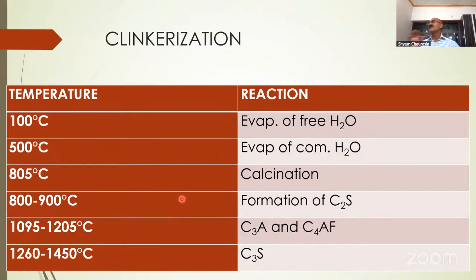That's C3A and C4AF. C3A is the tricalcium aluminate: 3 parts of calcium oxide combined with 1 part of Al2O3. They are the stable compounds, while those were the reactive compounds. First, you see some stable compounds in the form of limestone, bauxite, and iron ore. But those are converted into reactive oxides, and now again combination reactions are taking place, converting them into the stable compounds C3A, C4AF, tetracalcium aluminoferrite, and C3S.